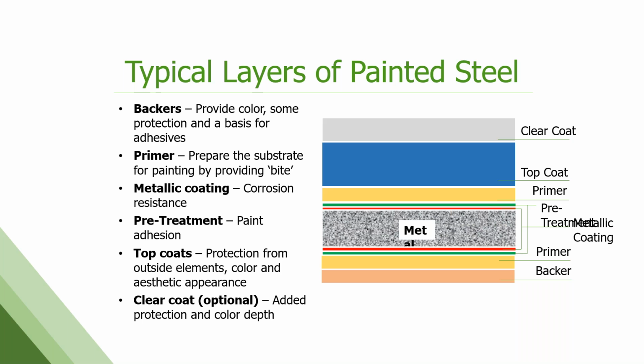So I want to talk a little bit now about the layers of a pre-painted metal panel, sort of starting with the substrate itself, which, like I said, is usually a metallic coated steel or aluminum. Sometimes you see stainless and some other substrates, but it's usually steel or aluminum. So working from the inside out, you have your base metal, let's say it's steel in this case, with a metallic coating, usually zinc or a zinc aluminum alloy, which we'll get into some specifics here in a few slides on that.